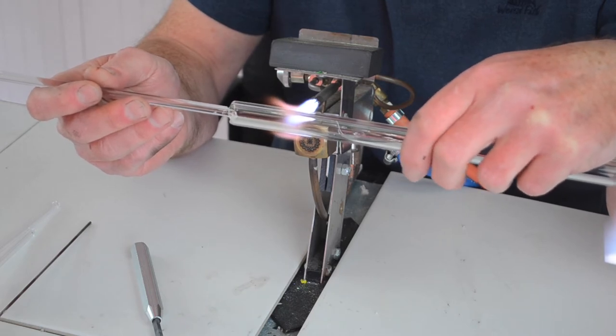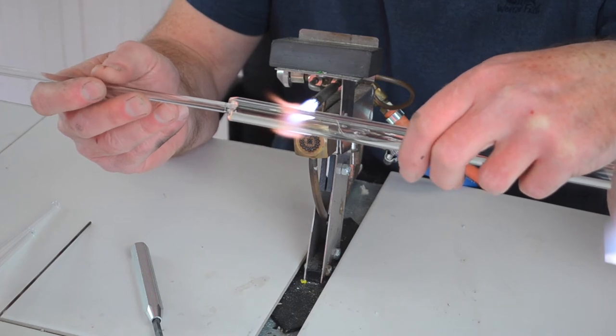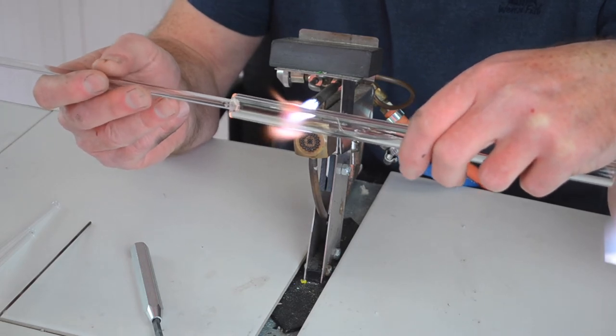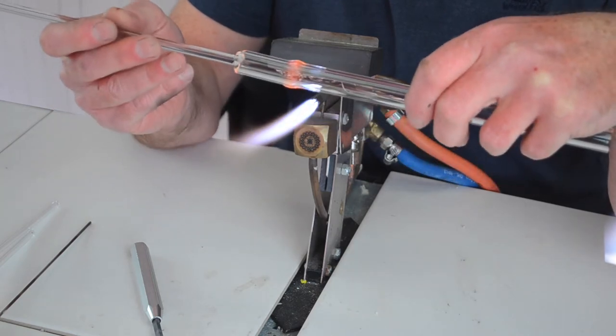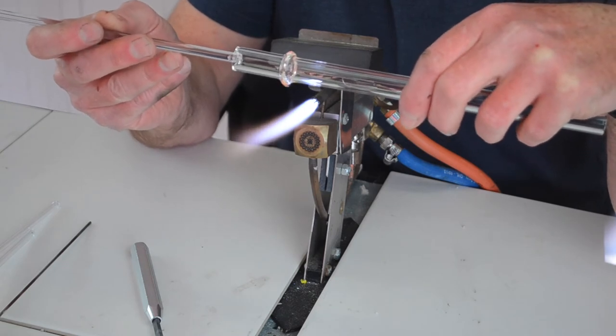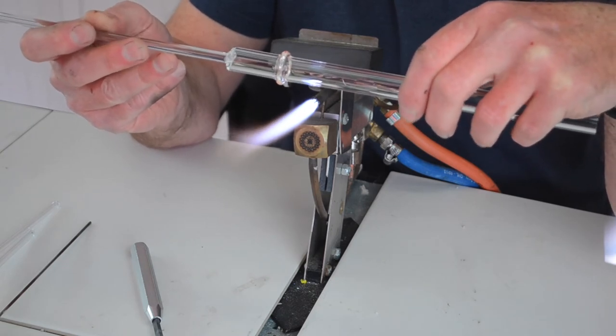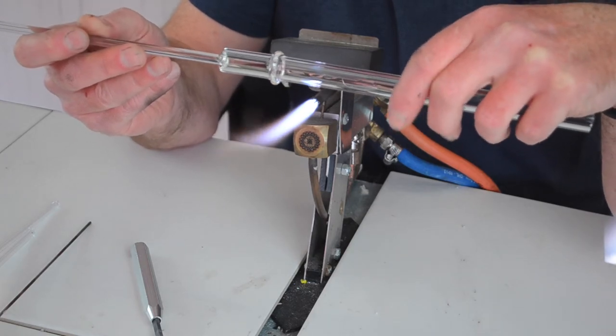And this reduces the stress in the glass, so just get the glass nice and warm, start to round, push it together and round it over, out of the flame, and then just push together to form this flange. We're going to try and increase the wall diameter by about 2mm, so now you've increased it to about 20mm, 22mm.